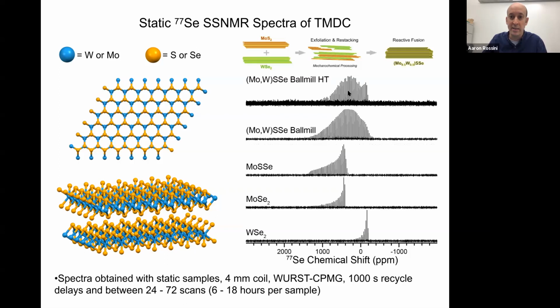Now, if we do the annealing, we don't see much difference in the spectrum. So this would maybe suggest that this cartoon picture here that our collaborators had originally developed is not quite accurate. There seems to be more mixing of the metals just during the mechanochemical step, even prior to the thermal annealing.